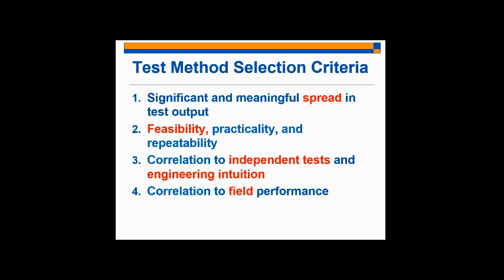And so when we think about developing this test to accurately screen these asphalt mixtures, there's a set of criteria that we must follow. And the first of them is we have to have significant and meaningful spread in our test output. So regardless of how scientifically sound our research is or how theoretically backed and proven our final product is, if it doesn't do a good job of distinguishing between mixtures, which we know are very different, both in terms of mix design and also performance in the field, if our test does not do an acceptable job of distinguishing between these mixtures and doesn't give us significant spread in our data, then it's not very useful.